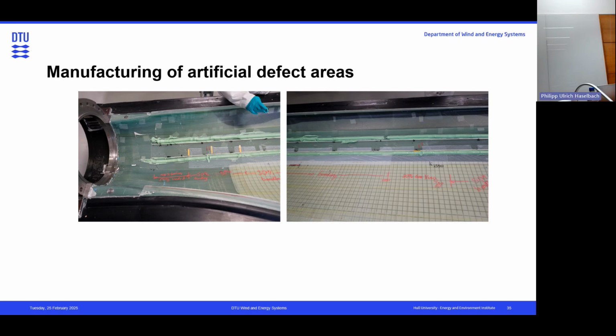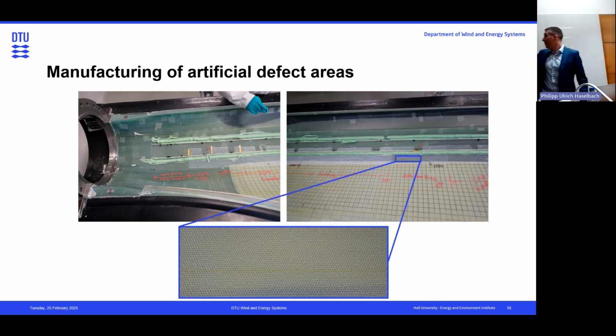That's what we, for example, also do in here, where you can see the adhesive applied for the shear webs. So it's a butterfly approach where you have two shells that are joined, and in between you have shear webs. And here we implemented some slip foils with a specific pattern, replicating that only 30 or 50% of the bonding is realized, like in real manufacturing, where not everything always lives up to reality, or to the wish as designed, let's say it like this. And then, of course, we incorporate this into our model and prediction, and later on we try to test it.